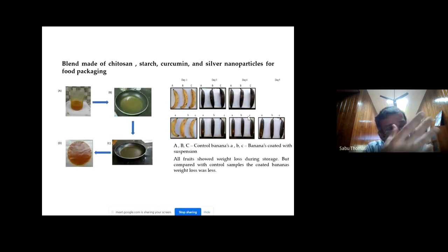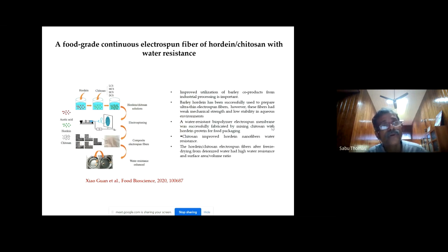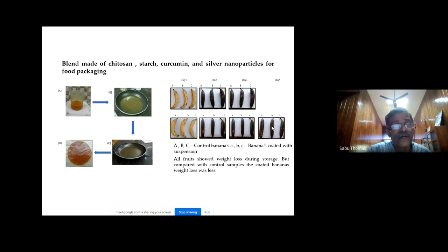Dear friends, we are also using nutraceutical compounds for food packaging. We are also into food packaging. You can see this is a combination of chitosan, starch, curcumin and silver nanoparticles. We made a very nice mixture of these and coated it on the banana. This is the uncoated banana. You see, the uncoated banana could not survive after 4 days. There is a lot of fungal growth. You don't see them after 4 days because they're degrading. But the banana coated with the suspension can survive up to 5 days and more. So this could be a very nice material for preserving our food.